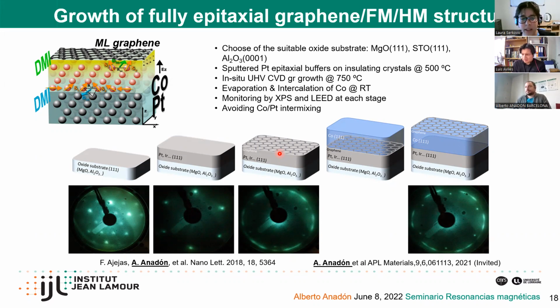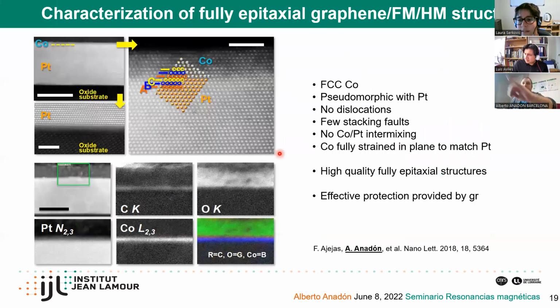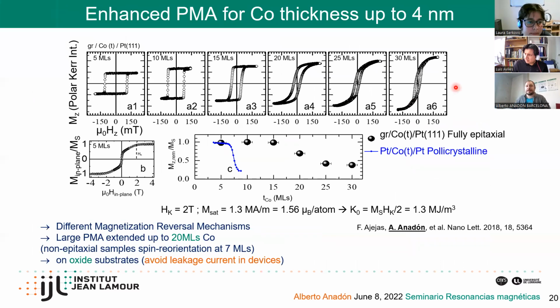Also, you say you put it on top of an oxide substrate, but you cover that oxide substrate with the metal to catalyze the growth of graphene. Okay. And then how thick is your cobalt for it to go through the graphene? So we have done, I think, up to 5 nanometers or so. If you have a very thick cobalt layer, then it's hard to do the full intercalation. So the thicker you want, the harder it is. But as you see here, we've done 4 or 5 nanometers, and the intercalation was almost 100%. But as you grow thicker, it's much harder.